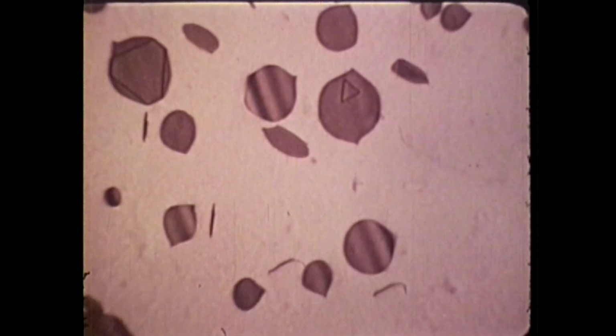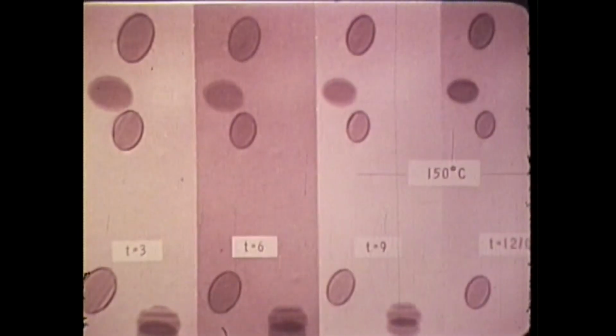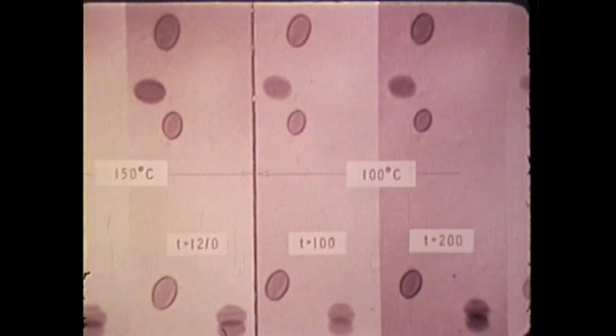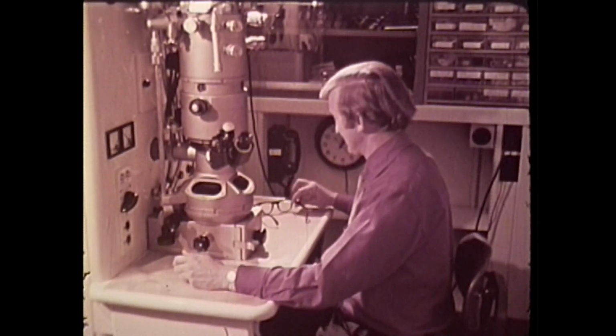The techniques we have developed allow us to make precise measurements and obtain detailed information on the diffusion of vacancies and their interaction with solute atoms. While it's well known that very small amounts of tin, cadmium, and even gold have an unusually large effect on aluminum alloy properties, we're trying to find out why. We are fairly certain that these trace elements strongly interact with the vacancies to modify the precipitation behavior, and we're trying to find the most effective elements for this purpose. When these studies are completed, we should have the potential for designing superior materials. Ultimately, what we're hoping to do with this research is to provide the parameters that can be used to program a computer. Given any set of desired alloy properties, a computer could then tell us the exact ratio of elements and the required physical operations to yield an alloy with just those properties.